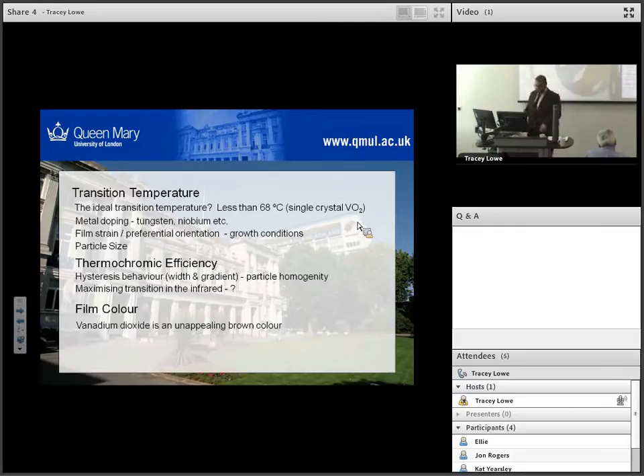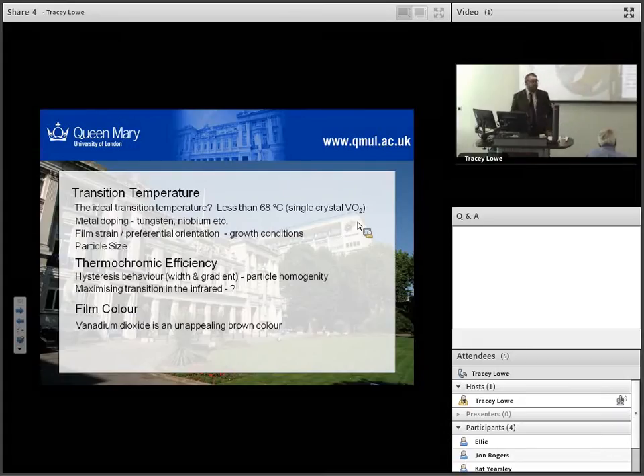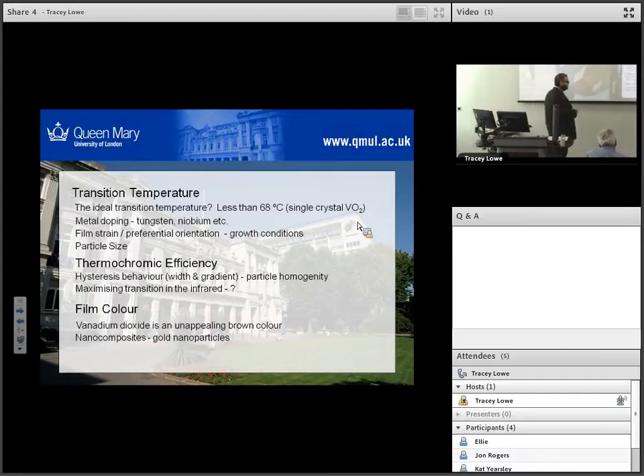The other issue is film color. Vanadium dioxide is unfortunately a pretty grim-looking browny yellow color, and no one in their right mind would want it on their window. So there's been some approaches that we've looked at, and other people have looked at, incorporating gold nanoparticles and taking advantage of the surface plasmon resonance of those to change the color is one way, or you can look at magnesium and fluorine doping like Granqvist's group in Uppsala University have done, shift the band edge into the visible, and you have a much nicer looking film. So there's some answers to that.